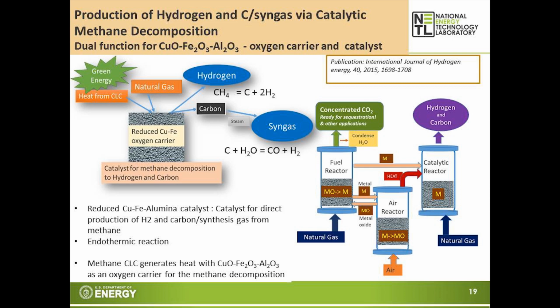And carbon is also a useful product, so we can stop here. Or if you want syngas, you can introduce steam for the carbon gasification to produce syngas, as shown in this equation. Now this methane decomposition reaction is an endothermic reaction, so it requires heat, and we can use the chemical looping combustion process with the copper and alumina to produce heat for the process.